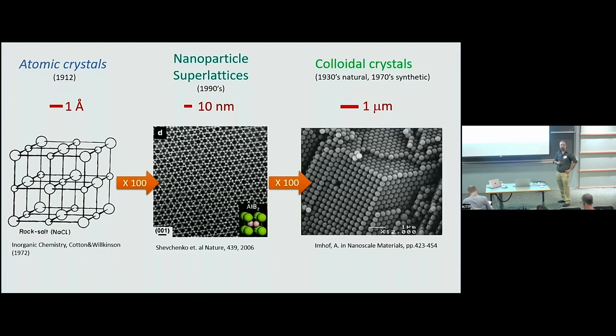There is no really clear connection between self-assembly here and the other two streams of length scales. And the reason for that is that there are some truly nanoscopic effects going on in nanoparticle superlattices. It has to do with the fact that in nanoparticles, the thickness of the ligand layer is similar in size to the radius of the core. And so those are some nanoscopic important effects.